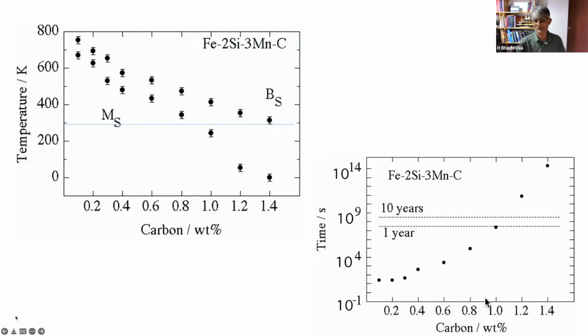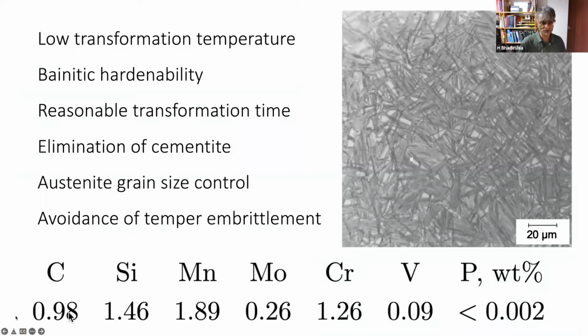So we made the material so that it would transform in 10 days at a temperature of 200 degrees centigrade. And it's a very, very simple composition. Carbon and silicon. We need some hardenability from manganese and chromium to avoid high temperature transformations. When you make a commercial steel, it's not possible to have very low concentrations of impurities like phosphorus. So you need that in order to stop embrittlement at the austenite grain boundaries. There's a lot of work done by McMahon in the US on temper embrittlement, and the same applies to any strong steel where the structure doesn't cross an austenite grain boundary, because you leave disorder at the austenite grain boundaries where impurities can segregate. So it's a very simple design of material, and this is the optical micrograph here.